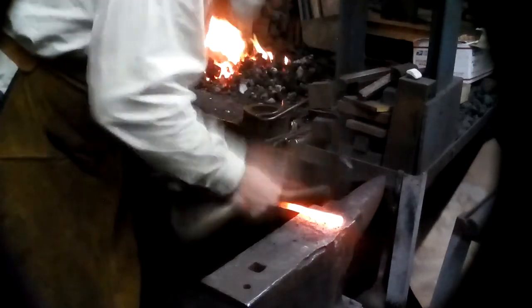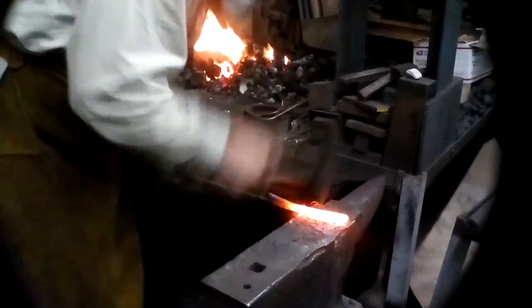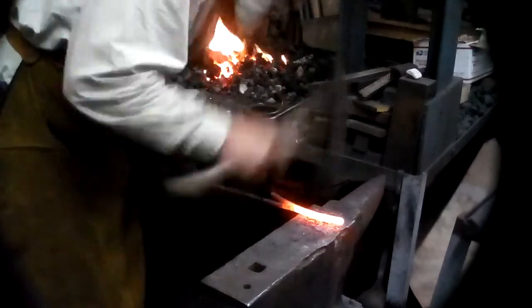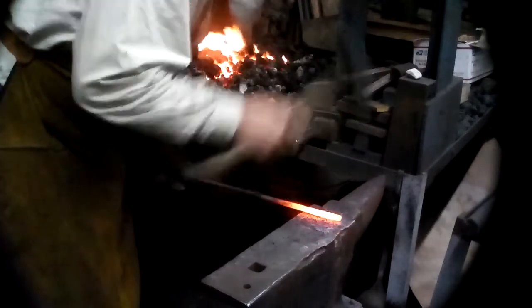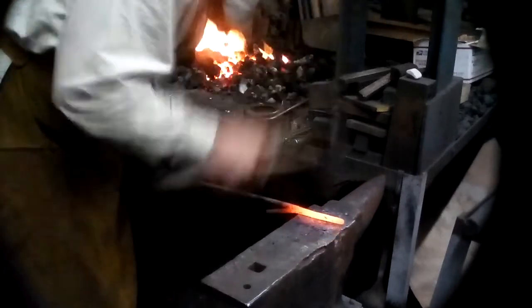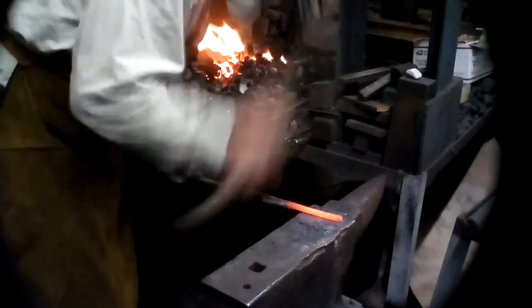You're not hitting this as hard as you can, because forge welding, if it's got the right temperature, does not take a huge amount of effort to get those two pieces to stick together. Now, unless you really want to forge a shape and take advantage of that high heat to help you, what you want is fast, light blows that you can control. But right now, I'm mostly using my wrist. And I'm consolidating this.